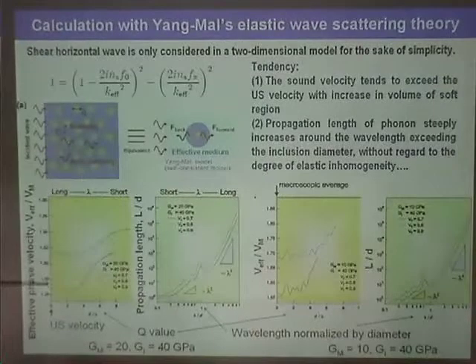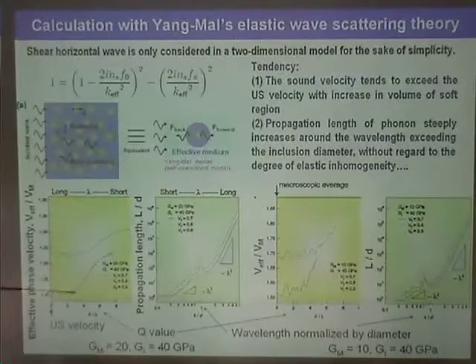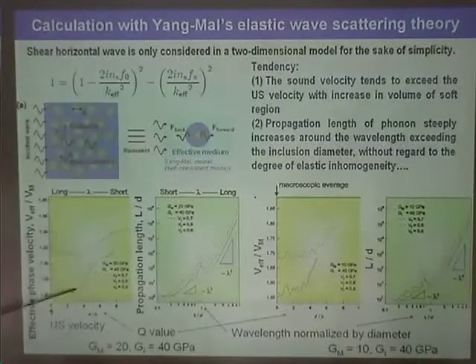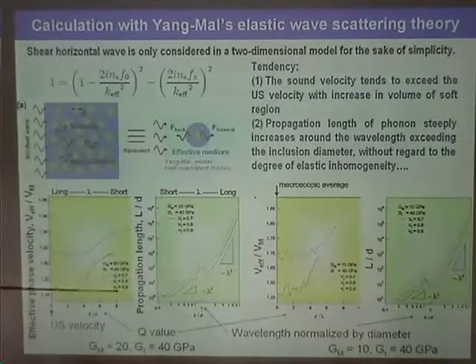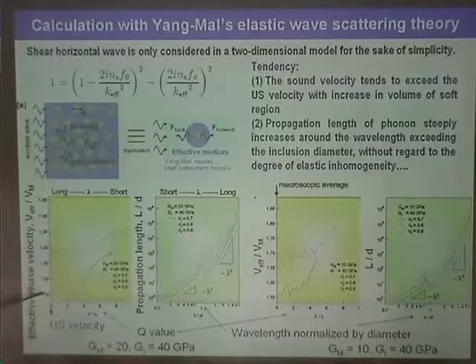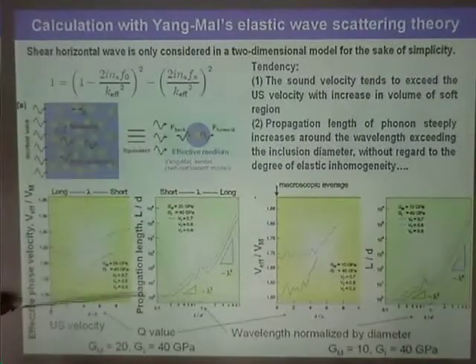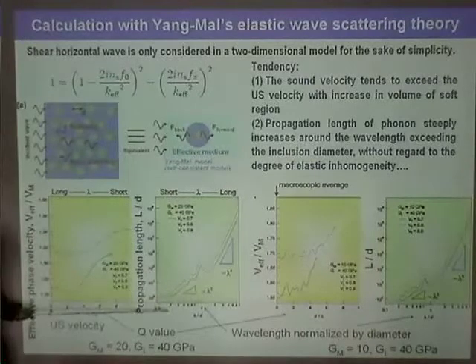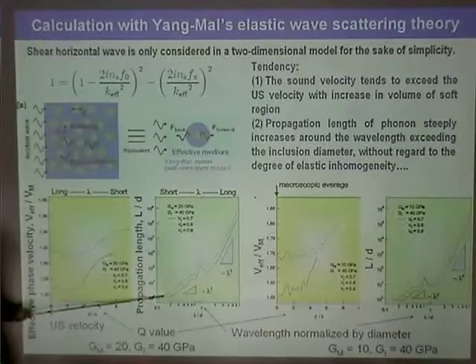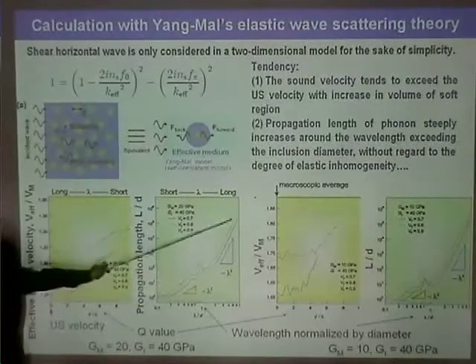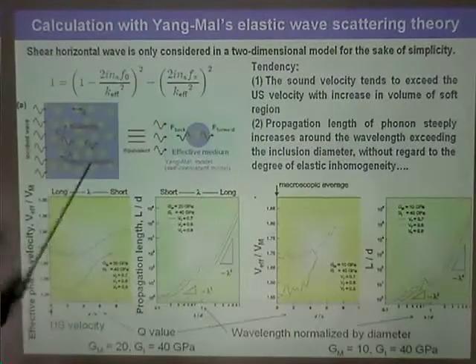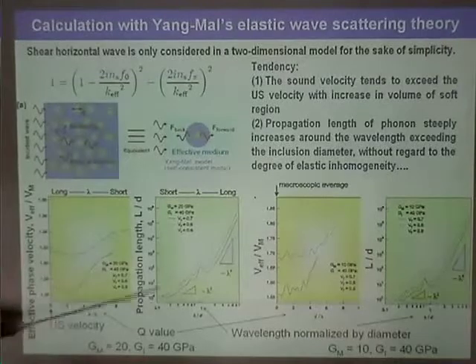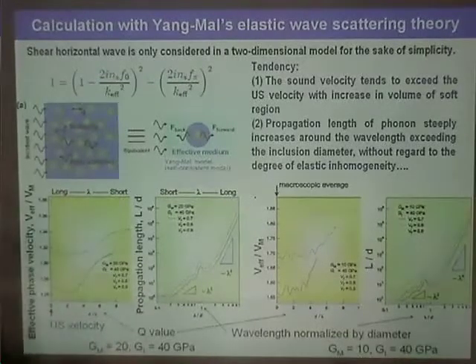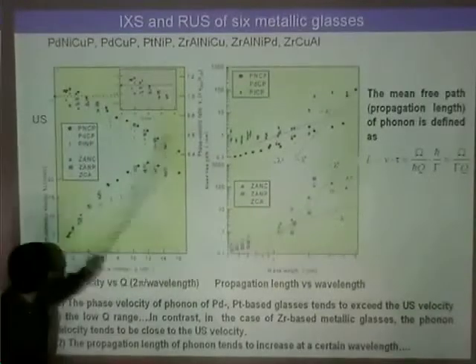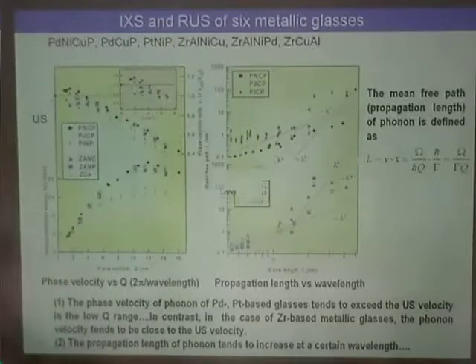So we can see that the phase velocity increases above the ultrasonic sound velocities. This point means the ultrasonic sound velocity. And in the case of the propagation length L, it increases slowly and then steeply increases around the diameter of the inclusions. This behavior can be very similar to this experimental result.